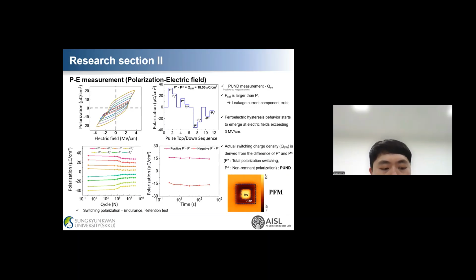So we first evaluated the ferroelectric properties of the plasma treated HZO. As shown in the left graph, the sample initially exhibits dielectric behavior, but as the electric field increases, polarization begins to appear. Once the polarization is formed, remanent polarization remains even after removing the electric field, confirming the ferroelectric behavior. To extract the intrinsic ferroelectric response, we performed PUND measurements and obtained a relatively high polarization value of 18.55 microcoulomb per square centimeter. PUND allows us to separate the pure ferroelectric switching component by excluding non-remanent polarization.